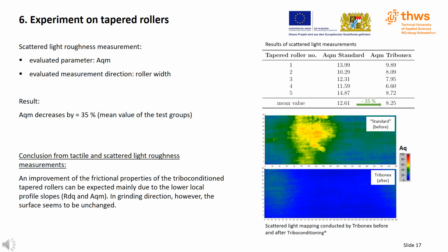From the tactile and scattered light roughness measurements, it can be concluded that an improvement of frictional properties of the triboconditioned tapered rollers can be expected. This is mainly due to the lower local profile slopes Rdq and AQM. However, the influence of the process on the surface in grinding direction is limited.